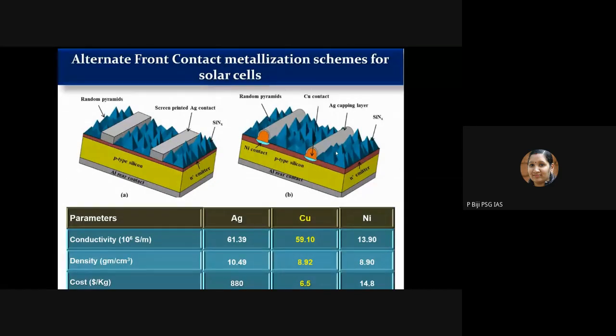In this case, the silver usage is going to be very less, but at the same time you have almost comparable conductivity. If you compare silver, copper and nickel, the conductivity is comparable. Silver conductivity is almost 61.39, and copper is very close, 59.10. So there is no significant decrease in conductivity, and you can actually use copper in place of silver. But the problem is that if you use copper as a metallization, there is a possibility that copper diffuses into the silicon.